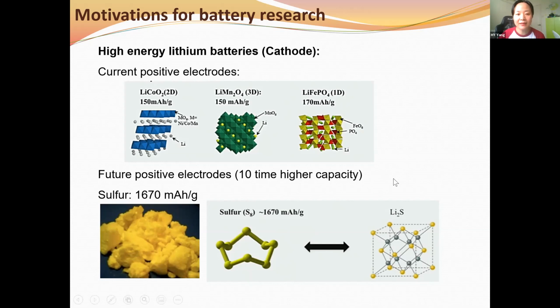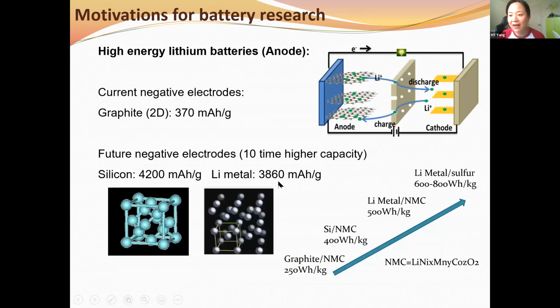And then the other electrode we are working on is the anode. Currently people utilize graphite. For example, in our laptops and our phones, we utilize graphite. This layer-shaped graphite, some people call that a graphene battery, but it is not a single-layer graphene. It is a stacked layered structure of graphene, and that can give you a few hundred milliampere hour per gram, 370 to 400.